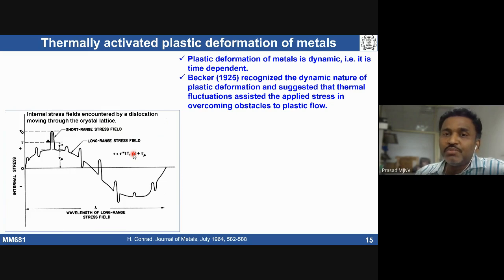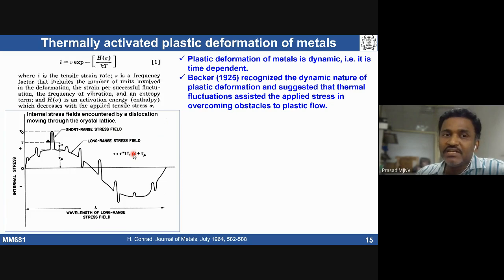In 1925, Becker mentioned that strain rate can be given in the form of an Arrhenius equation. Strain rate is equivalent to some frequency factor nu times exponential of minus delta H of sigma by kT. This H of sigma, a function of sigma, is called the enthalpy, also called the activation energy for plastic deformation. k is the Boltzmann constant, T is the temperature on the absolute scale.